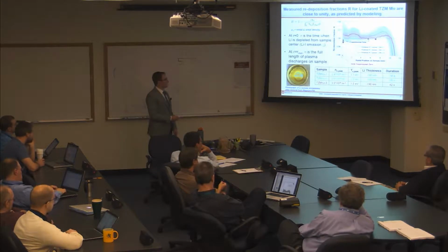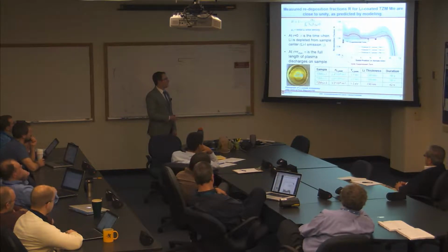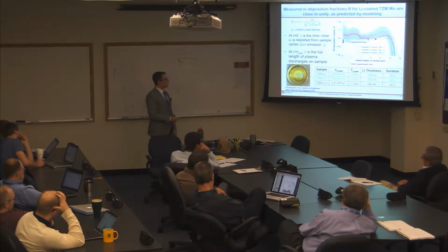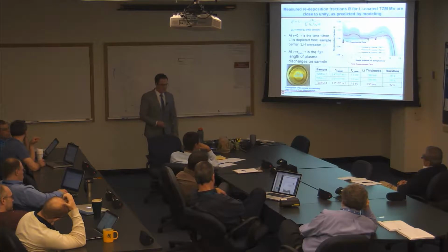So all of these redeposition fractions were very close to unity, greater than 0.99, and the predictions of the model are overlaid here. So basically I did some smoothing on the predictions, and the bands here are the standard deviation from the actual variance that you see. But I smoothed it, and as you can see, notice the suppressed zero here also. So this only goes from 0.98 to 1.02, and the experimental measurements are very close to the data.